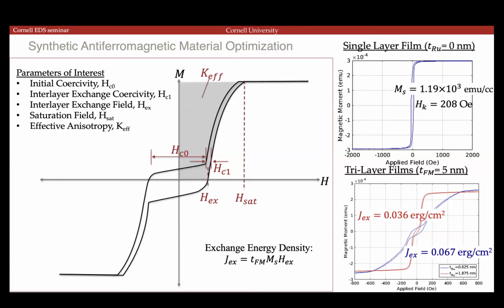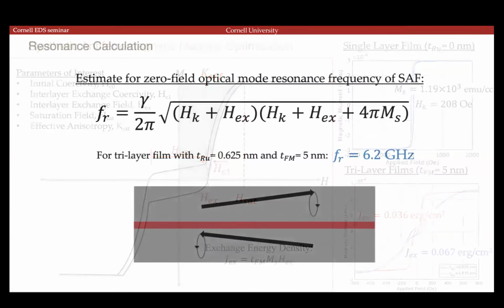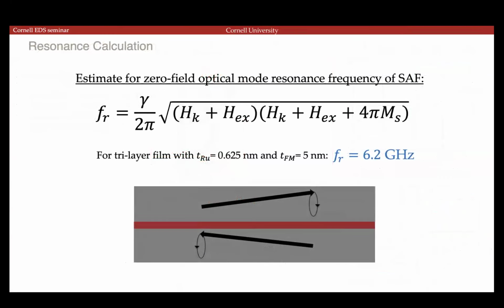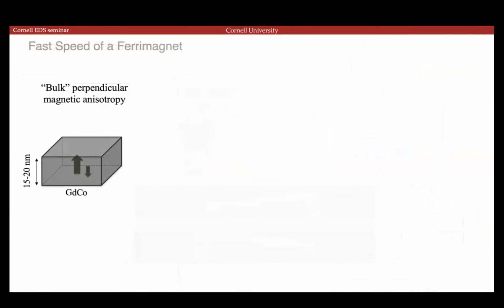So we can optimize these and get, at this point, for our initial films, only a resonance frequency of 6.2 gigahertz, but anything higher than that, it's possible that we would see other complications as well. So this initial film did increase the bandwidth of cobalt iron boron with an antiferromagnet, but not as much as we wanted. So we also looked into ferrimagnets.